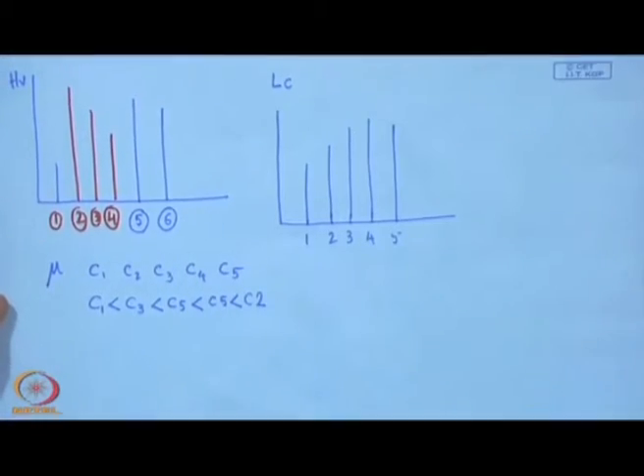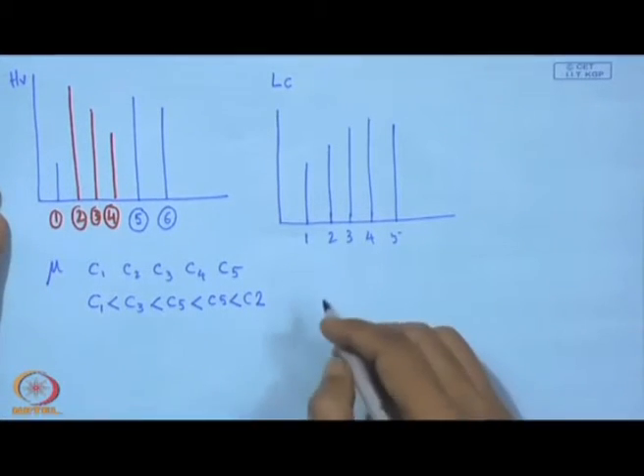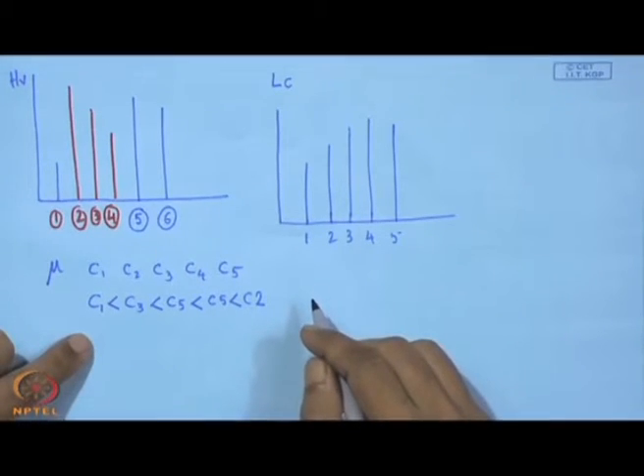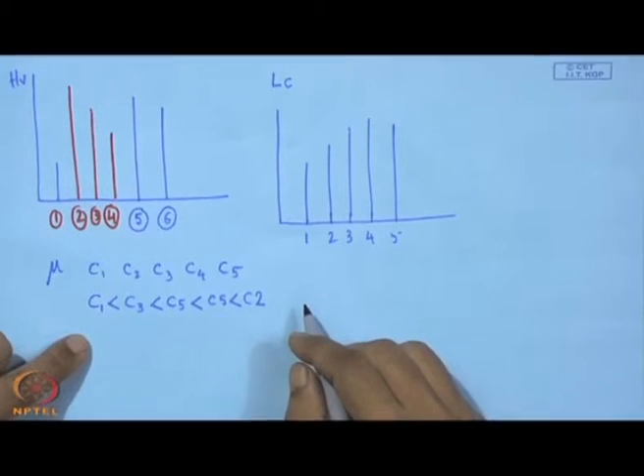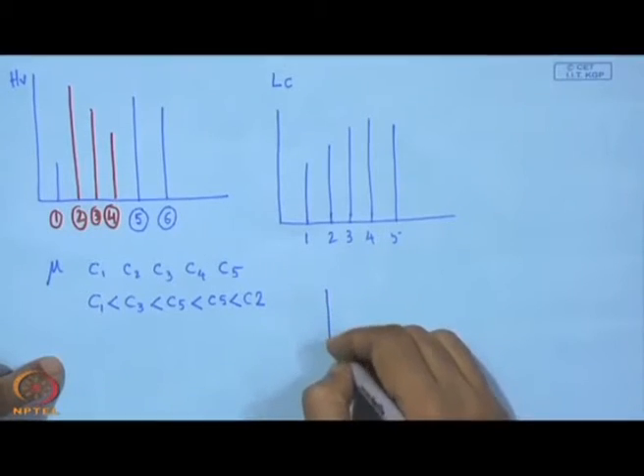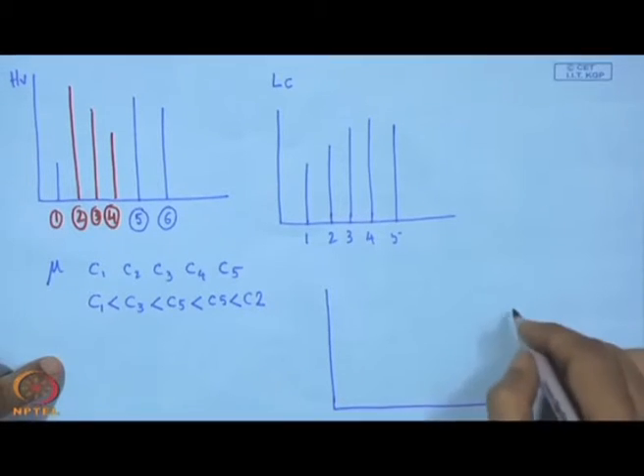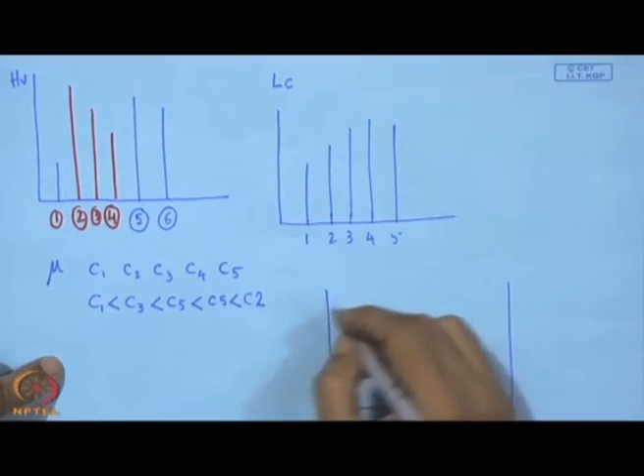Now, apart from that, what is also important for us to know is the wear coefficient. Wear coefficient is actually the wear on the track, that is, on the disc which is coated. On that disc we have a wear channel, and from the depth of that channel we can determine the wear coefficient. We have already discussed that it is the volume of wear on that circular wear track, divided by the normal load applied times the distance travelled. So, we can just show this. This is the wear coefficient.